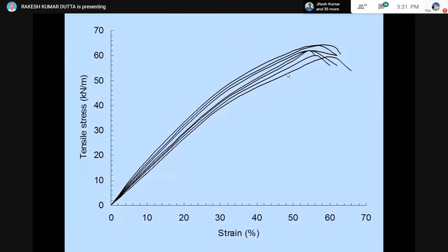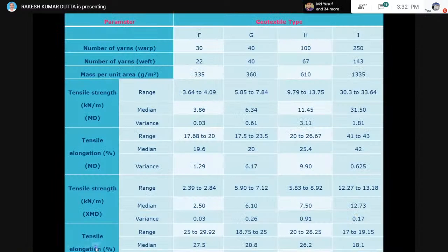So here you see all, 1, 2, 3, 4, 5, 6, there are 7 different curves that were tested. So every curve is actually showing you a different value of the tensile strength, because this difference you are getting is because the yarn used at different locations for the woven geotextile may not have a similar diameter. So that's why you are getting different tensile strength values. Even the strain at failure, you are getting a little bit of variation. Now the question is which value of the tensile strength and the strain is to be picked up or reported. So for this we need to perform the statistical analysis.